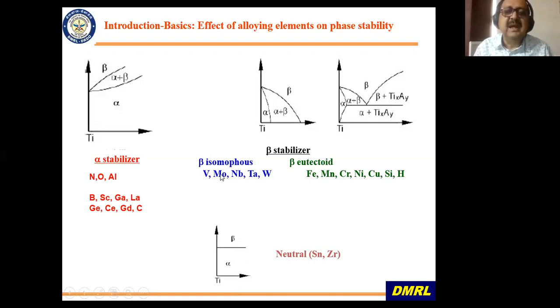And the elements that are in the beta isomorphous category are vanadium, moly, niobium, tantalum, and tungsten. And in the eutectoid category is iron, manganese, chromium, nickel, and also hydrogen, which is one of the gaseous elements which stabilizes the beta phase.